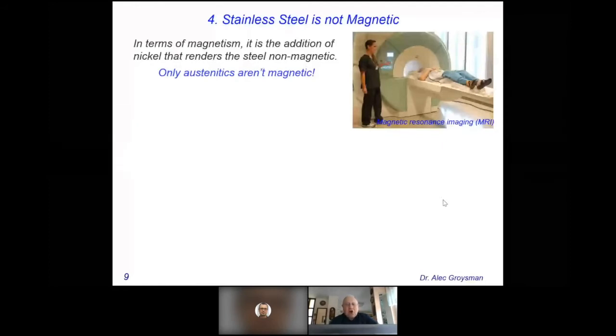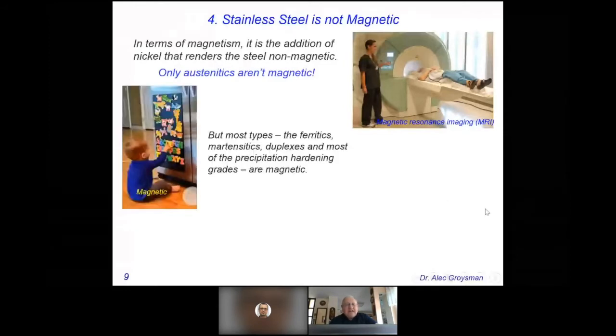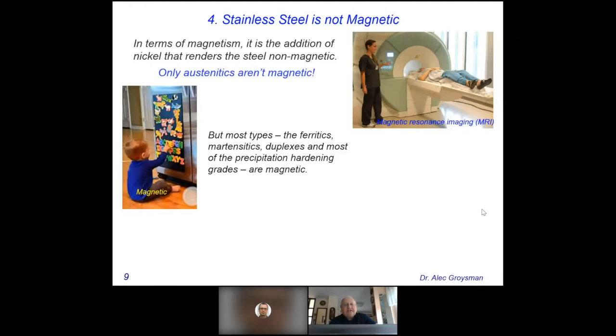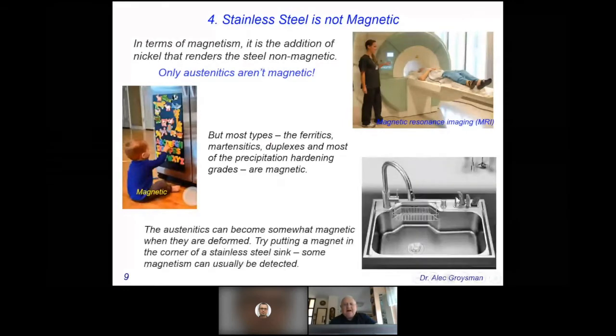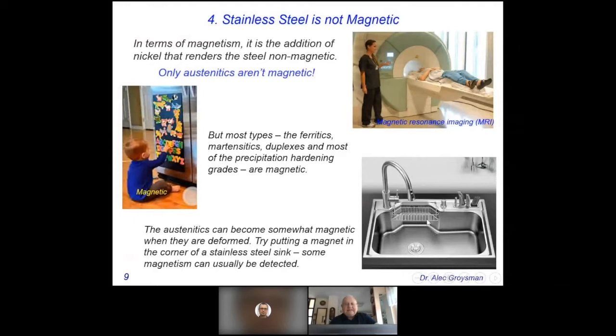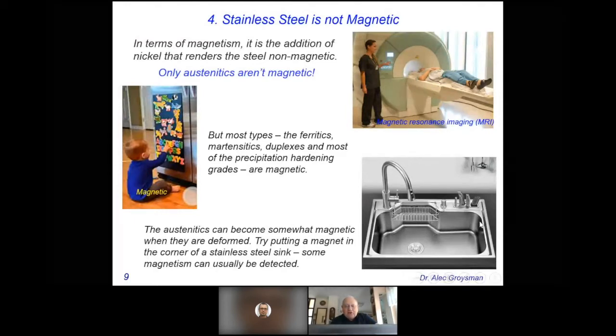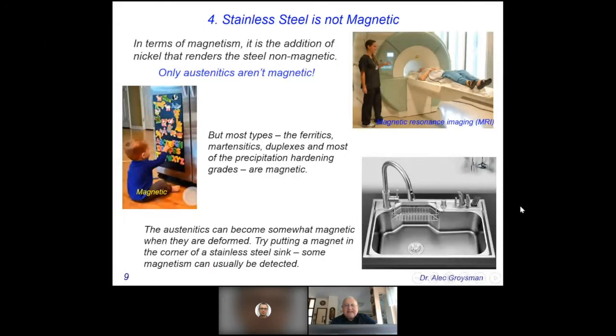Let me share my personal note. Austenitic stainless steel is a natural, unusual, metastable state. At room temperatures, ferrite is stable. The addition of nickel and manganese makes austenitic steel stable at room temperatures, but the austenitic can become magnetic when deformed. Cold work and welding are liable to increase the amount of martensite and ferrite respectively in the steel. After deformation, it is work hardened steel. Try putting a magnet in the corner of a stainless steel sink. Some magnetism can usually be detected.